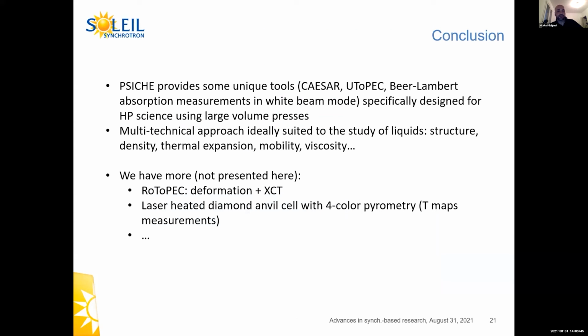So in conclusion, PSICHE provides some unique tools, CAESAR, UToPEC, Beer-Lambert absorption measurements in white beam mode, specifically designed for high pressure science using large volume presses. We have a multi-technical approach ideally suited to the study of liquids: structure, density, thermal expansion, mobility, viscosity. We have much more. I cannot present everything, but we have also implemented the ROTOPEC, which is another device for tomography, not high speed this time, but a very strong, very nice tool to get the deformation and X-ray computed tomography. We have also a laser heated diamond cell, and we have developed the 4-color pyrometry for this setup and other stuff.